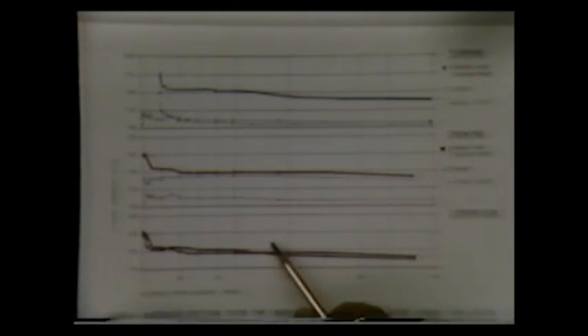Although the straightening machine setting was identical, the strength increase caused by straightening after drawing was less than that after turning. That is because the material has already been work hardened during drawing. As shown in the bottom diagram, the strength pattern over the cross-section shows no significant difference irrespective of whether the 1035 grade was turned and straightened or drawn and straightened.